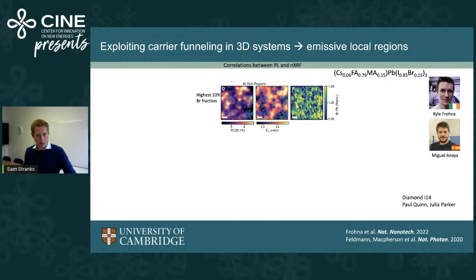What we see, first of all, is that the regions that are high PLQE, PL quantum efficiency, are very low Urbach, which is what we would expect. So when there's less electronic disorder, we have higher luminescence. And when we look at the bromine fraction, overlaid in the blue, you see that it correlates with the high PLQE region. So where we have strong luminescence, we have slightly more bromine rich.